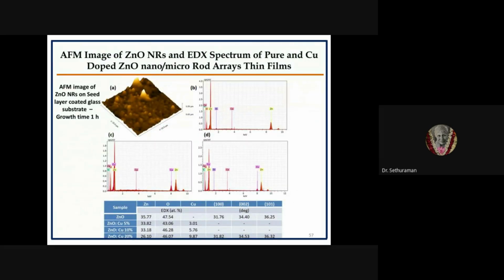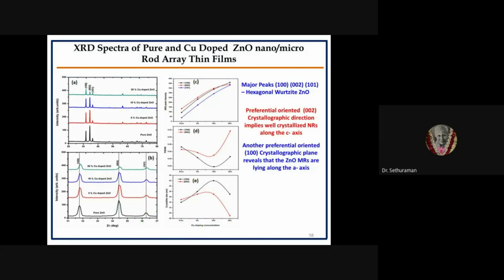So this AFM image shows the surface roughness and the uniform distribution of nanorods on the seeded glass substrate. And we found the stoichiometry of the zinc oxide at different places of nanorods as well as microrods is completely retained in all the nanorod surfaces and places.